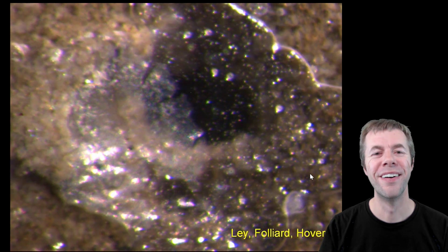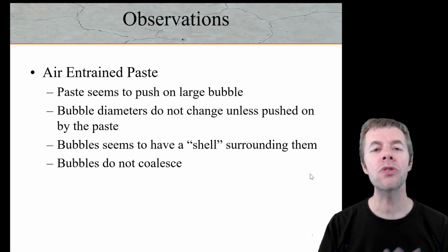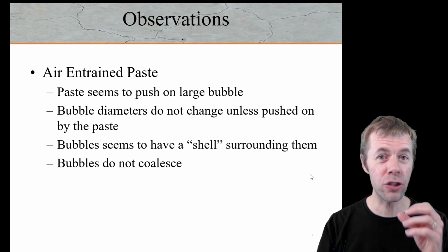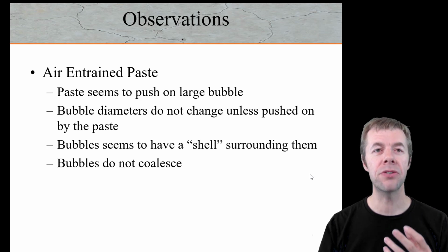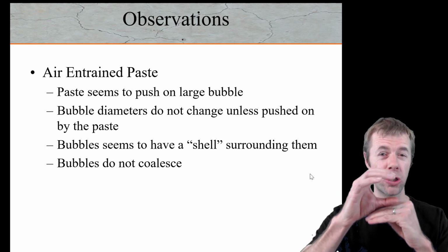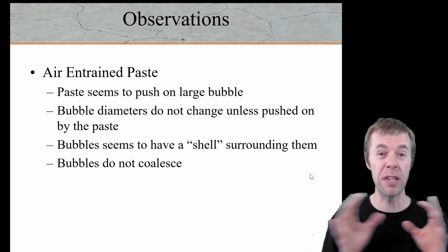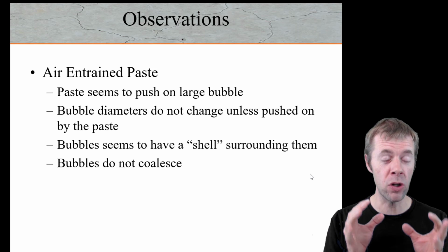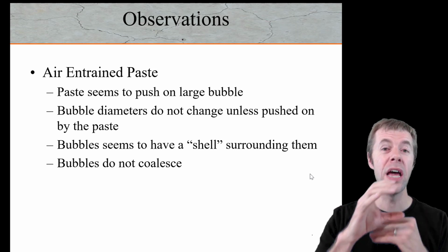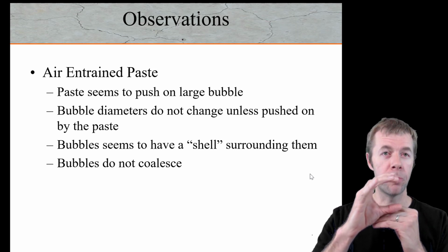Pretty cool video, huh? Let's talk about what happened. That was air-entrained cement paste. The paste seems to rise up and push on this large bubble. And the diameters do not change over time. The diameters were pretty constant. I don't know if you noticed that or not, but the diameters didn't change until the bubble was pushed on.